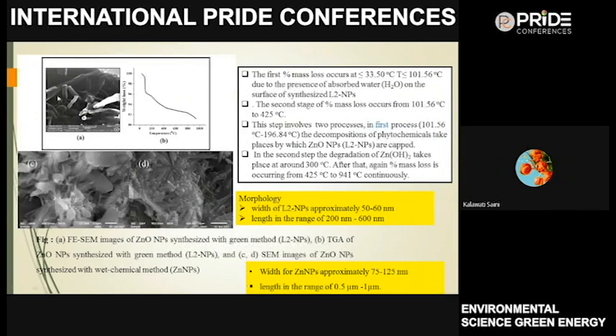These are the FESEM images regarding the green synthesized nanoparticle L2 with 2 ml of leaf extract. This is the TGA, thermogravimetry analysis, and these are the same images regarding zinc oxide nanoparticle by the chemical wet method. Here, first is a sharp mass loss. The first mass loss is seen from 33.5 degrees to 101.56 degrees centigrade, which is due to the presence of adsorbed water, H2O.